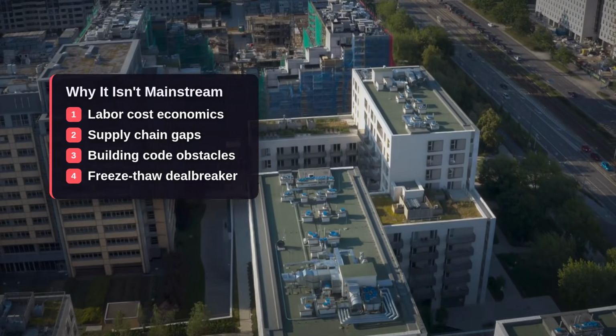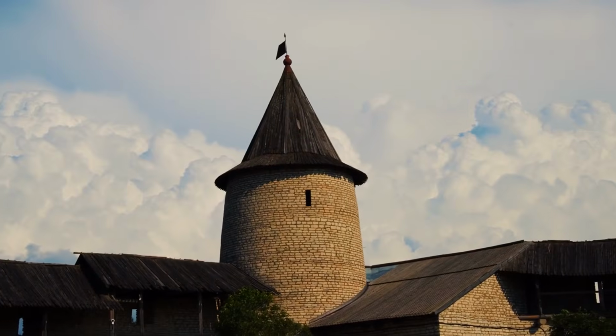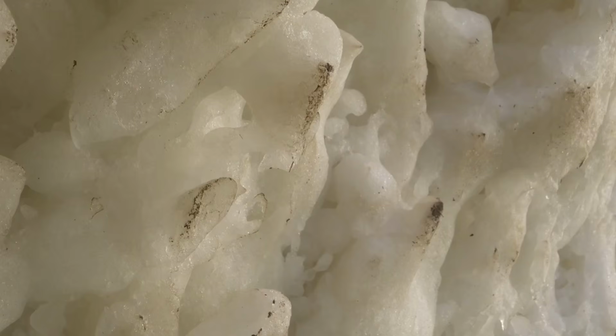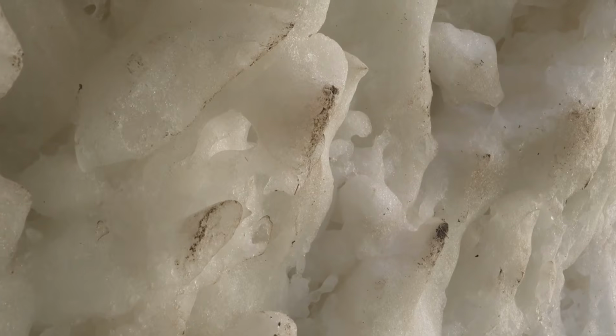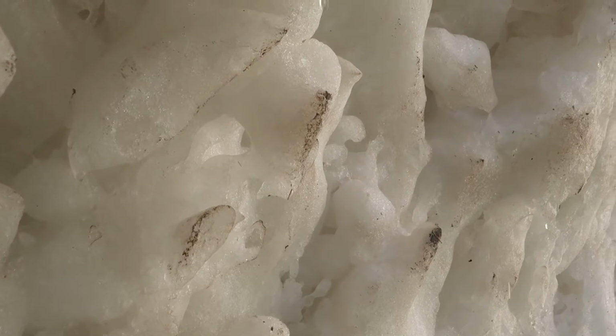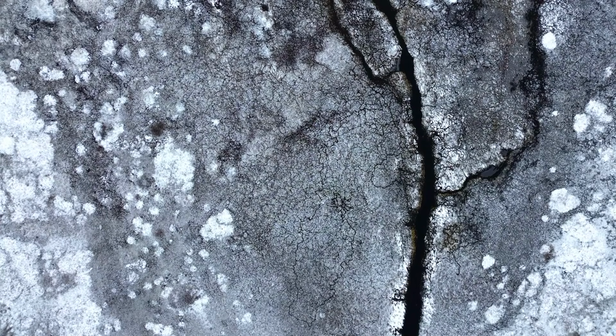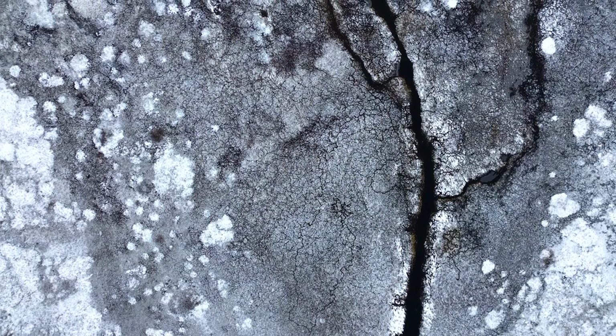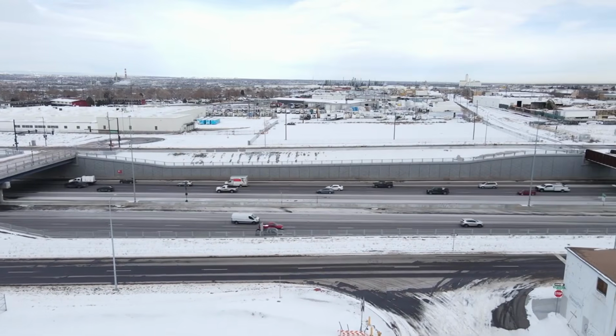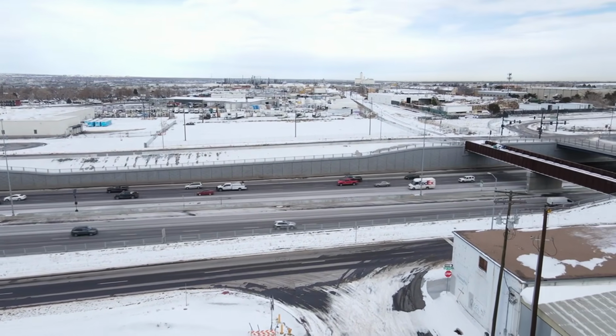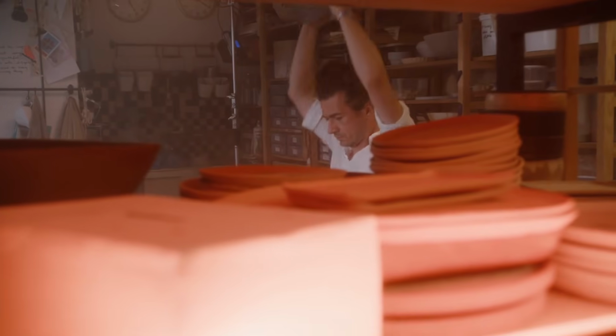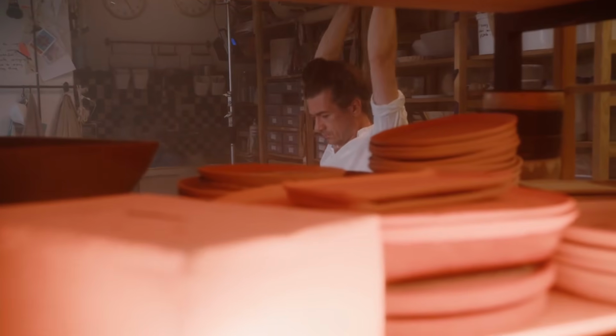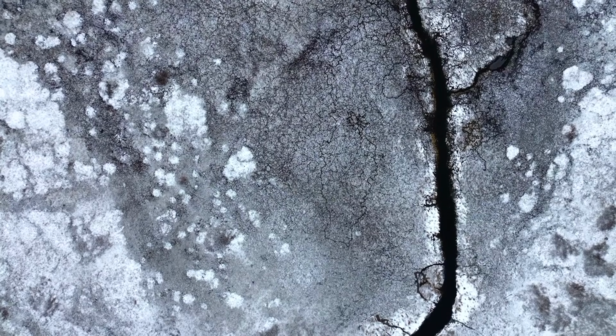The fourth barrier is the hardest one, because it's physics, and you can't negotiate with physics. Clay pot filler slabs are vulnerable to freeze-thaw cycling. Any porous material, and the clay pots in a filler slab are, by design, slightly porous, will absorb trace moisture over time. In climates where temperatures cycle repeatedly below 32 degrees Fahrenheit, that moisture expands as it freezes, generating internal pressure that eventually fractures the clay. A single winter in Chicago or Denver will begin degrading unprotected clay pot voids within the roof slab. After 5 to 10 freeze-thaw cycles, the structural integrity of those voids is compromised, and the roof has to be evaluated. This is the non-negotiable dealbreaker.